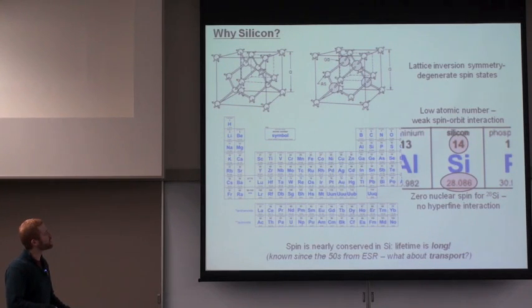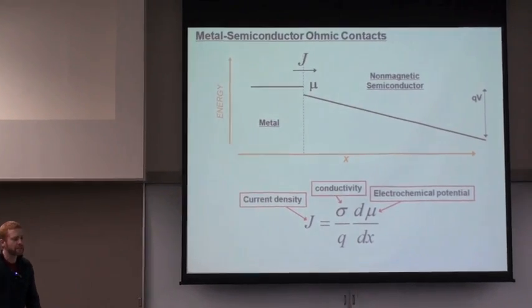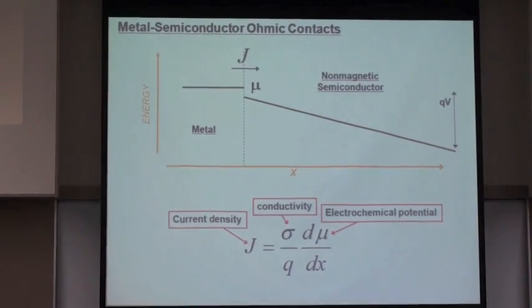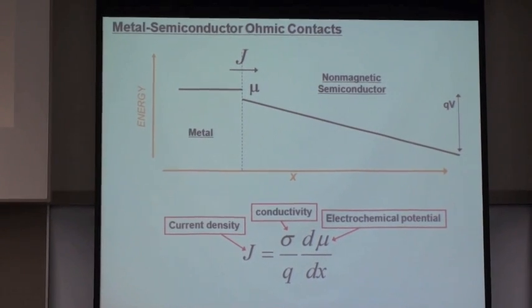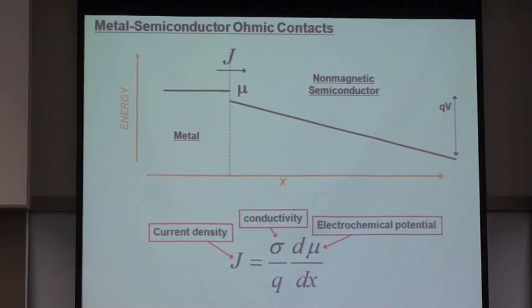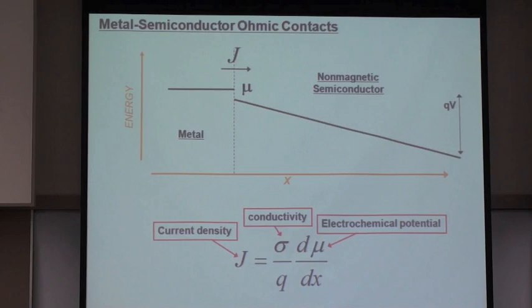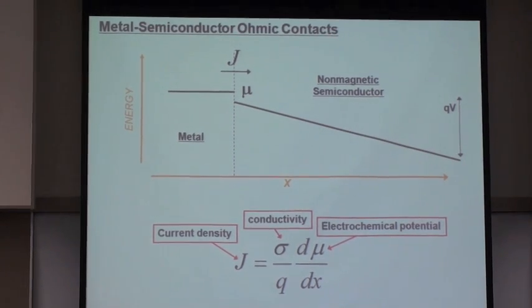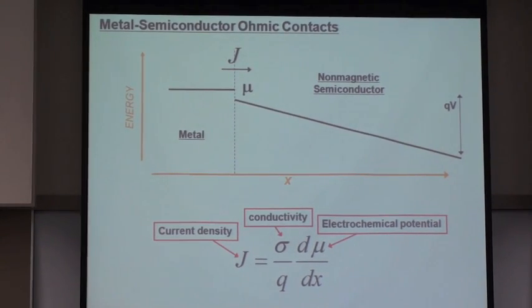So the way that I'm suggesting here that you might approach it is through ohmic injection. We would propose then to take a ferromagnetic metal, one in which there's more spin up than spin down, and just form an ohmic contact with our silicon, apply a voltage, and then expect perhaps that the imbalance would be maintained across the interface. So first we have to remind you of how ohmic transport works. This is a process which is driven by a gradient in electrochemical potential, and it's proportional to the conductivity.